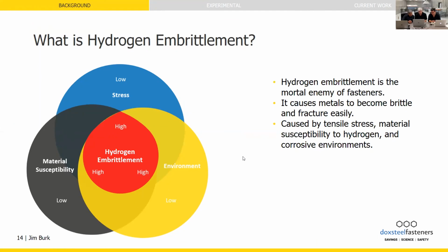But let's recall that when you look at risk from hydrogen embrittlement and avoiding the types of failures that I discussed earlier, you're looking for layers of protection. You're not looking necessarily for just one way of prevention, like using a bolt with a Rockwell C50 and then putting nickel-cobalt on that. You might want to think of using layers of protection, using a bolt that has lower hardness that's been shown not to fail, and using a barrier coating such as nickel-cobalt. Because in the third failure, the hardness readings on the bolts all passed because they didn't detect the zones of high hardness. The nickel-cobalt would form another layer of protection that would potentially have prevented that failure.